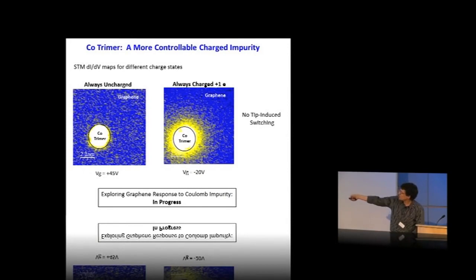Here, for example, the cobalt trimer, we can gate the cobalt trimer such that when we bring our STM tip and image the electrons around the trimer in a particular charge state, the trimer stays in that charge state. So we can put the trimer into different charge states, and then we can map out the electrons around it, and the charge state will not change. And so for us, that's progress. This is a work in progress. We're not done, but we're very excited about this, because now we're starting to map out what the electrons are doing around these Coulomb impurities, and we can control the charge on these Coulomb impurities. So now we have a chance of actually testing some of these ideas.